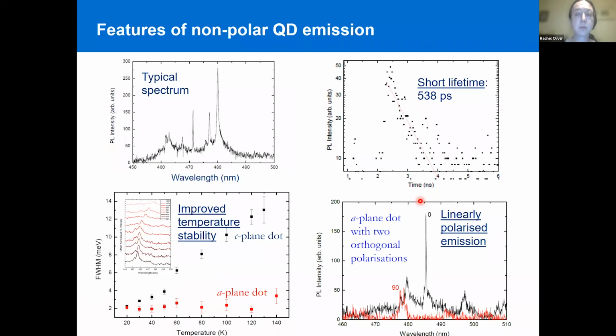And those quantum dots, once we complete the droplet epitaxy process, show typical spectral features of quantum dot emission. We have these very sharp peaks. So this atom-like nature gives us a delta function-like density of states in the quantum dot. And that means that the emission from a single state in a single quantum dot is really a spike, very sharp.